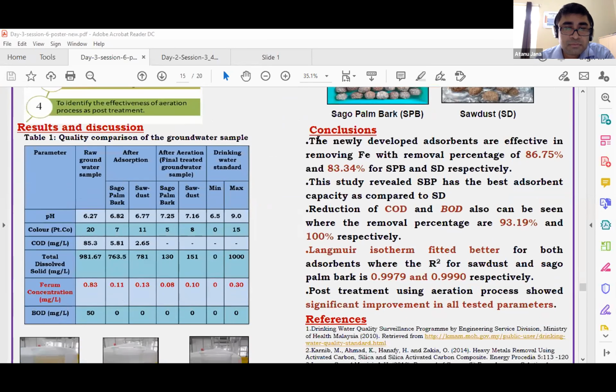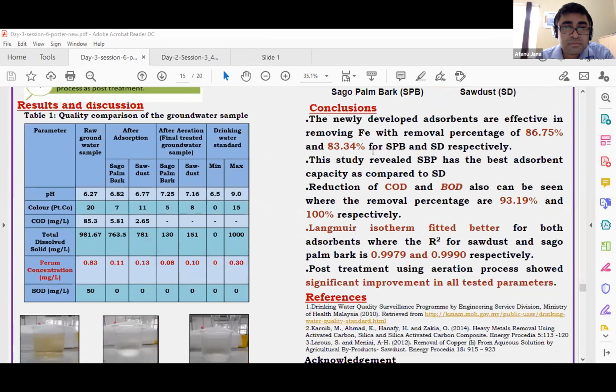Okay, so this is for results and discussion. It can be clearly seen there is significant improvement, especially in the concentration of ferrum. The initial concentration of ferrum in the raw groundwater sample is about 0.83. Then the improvement can be clearly seen here, where the concentration of ferrum has been reduced by more than 65% to 0.11 and 0.13 for sago palm bark, and sawdust respectively.